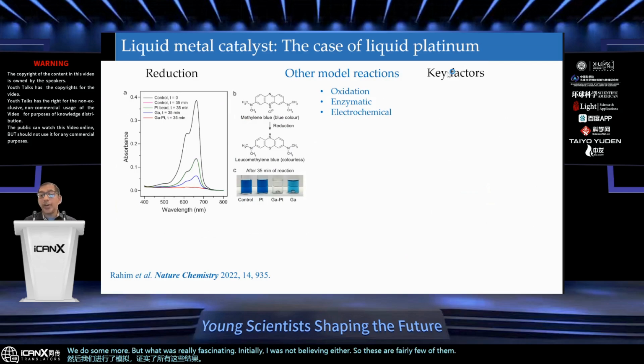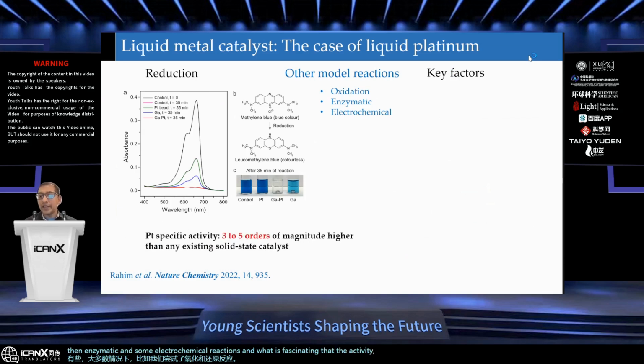So these are a few of the model reactions that I checked with this liquid platinum. It was fascinating enough that in most cases, we tried oxidation and reduction reactions, then enzymatic and some electrochemical reactions. And what is fascinating is that the platinum specific activity that we get, despite the platinum solubility in gallium at 50 or 60 degrees being really, really low, is 3 to 5 orders of magnitude higher than any existing catalyst, including the single atom solid catalyst. So 3 to 5 orders of magnitude is just massive. It appeared to me that it can solve the real problems of our life. Anyway, that was a start for this sort of work.